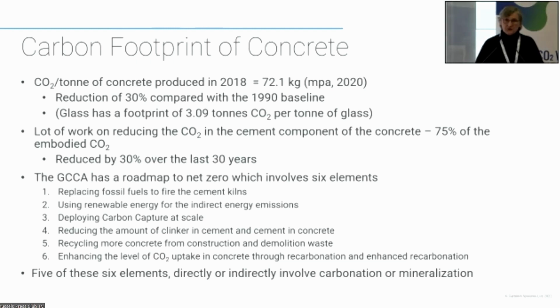There's been an awful lot of work on trying to reduce the CO2 in the cement component of the concrete. So if you think of the embodied carbon dioxide in the concrete, about 75% of it is due to the cement. And that has reduced by 30% over the last 30 years by the major changes that the cement industry are making. A lot of that is driven by the Global Cement and Concrete Association, and they have a roadmap just recently published, which involves 6 different elements.